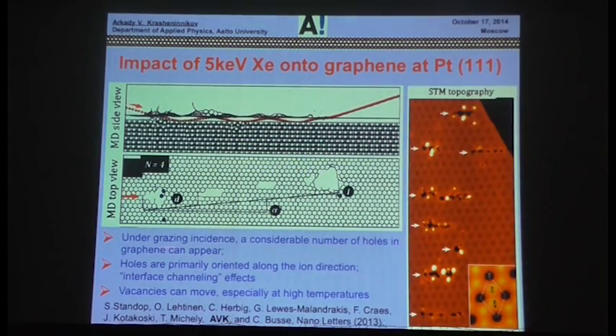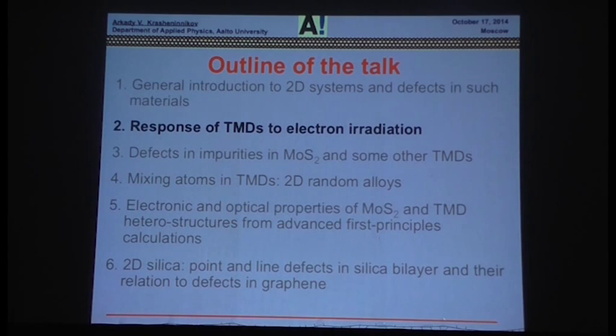This is the top view, what you get in calculations, and this is what you have in experiments. The ion beam comes from the left. You get pretty much the same holes, and if you heat up the system later on, the vacancies will migrate and coalesce, and this way you can make a nano mesh. These are very interesting results with potential applications in nanoelectronics, a way to open a gap in graphene. Okay, but let's move on to transition metal dichalcogenides.